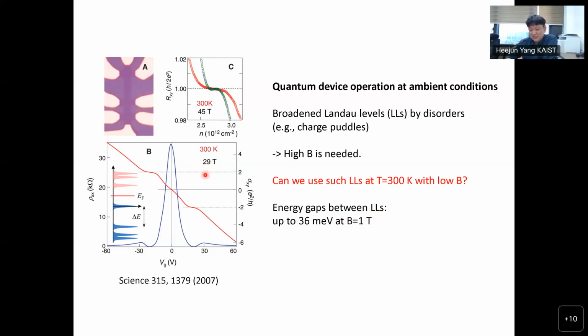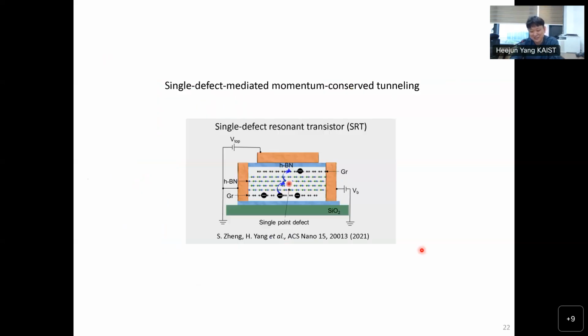So what's the reason? We also know the reason: the charge puddles. If we make this nice graphene device, this is another important property of 2D materials. We have a highly doped region and a less doped region, and they are making charge puddles. So all Landau levels are being broadened by the charge puddles. So we need a very high magnetic field. So what can you do about that? I developed this single defect resonant transistor, which is interesting. This is based on resonant tunneling as well.